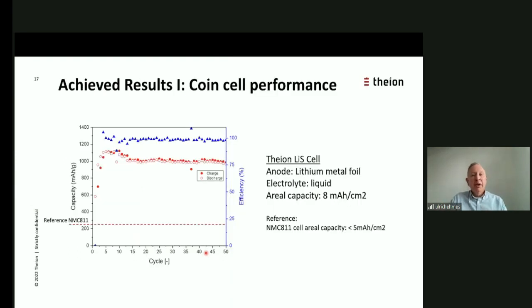So, achieved results. In the battery industry, you first start to design coin cells, so 18 millimeter small cells. And you can see here, remembering this high energy density of over 1,000 milliampere hours per gram, we have achieved more than 1,000 milliampere hours per gram. And the reference is NMC 811, it's here below. And we have now cycled over 50 cycles. So we are absolutely on the right track with an areal capacity of 8 milliampere hours per square centimeter.